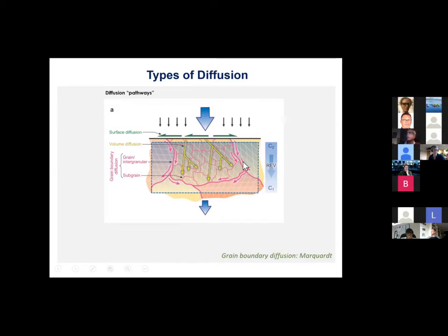But the point I wanted to make here is that even if you have a rock with grain boundaries and surfaces, you can treat that whole thing as a representative elemental volume, as one averaged volume of some sort. And you can look at the flux of atoms coming into this volume and going through all of these different individual steps, diffusion within the lattice along different directions, diffusion in grain boundaries, diffusion on the surface, and average all of that, and you get a flux that comes out. And you can treat that process also using a diffusion equation.